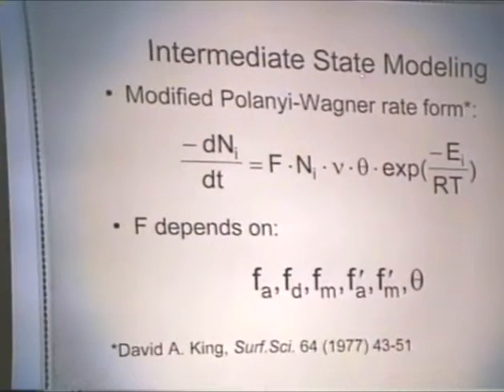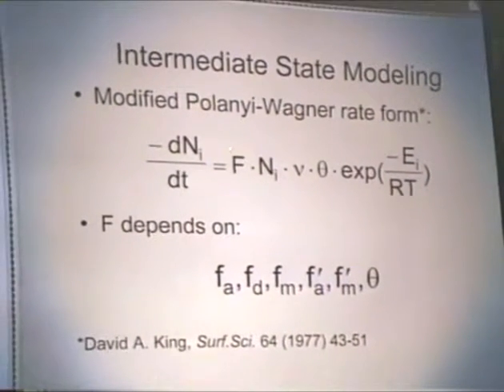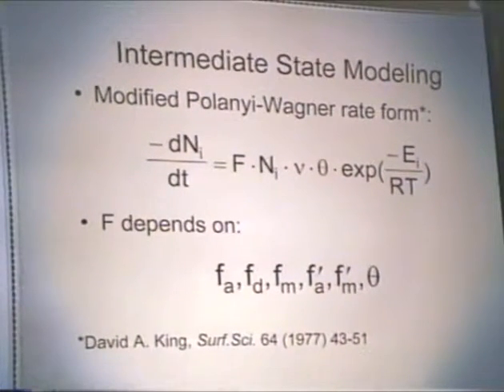This is the modified Polanyi-Wagner rate form we use to model the intermediate state. The modification is in this factor F. F represents the portion of desorbing species in the precursor state that actually make it off the surface, that actually desorb from the precursor state. If F is 1, then that means any species that gets into a precursor state desorbs, and you just see regular first-order desorption kinetics.